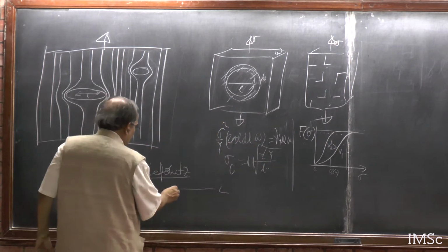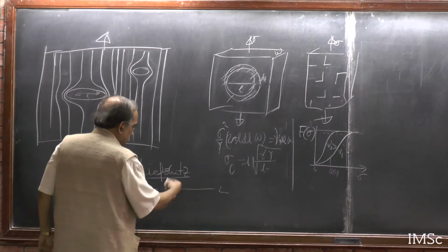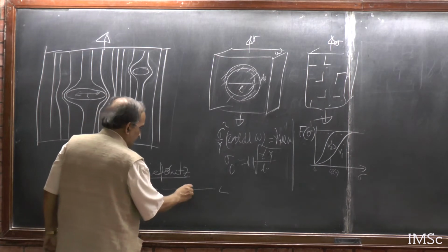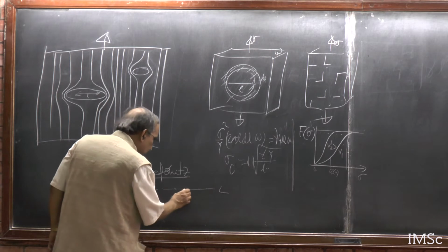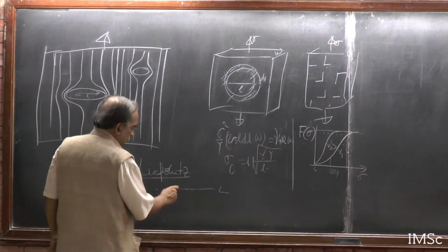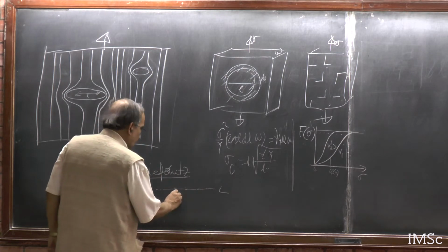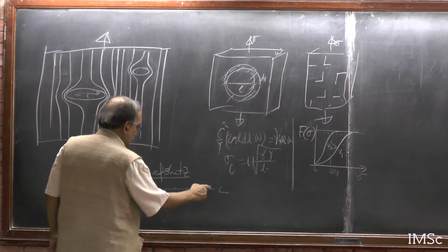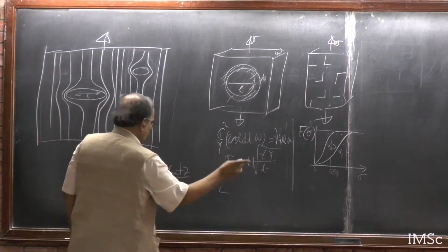And a simple argument was that if you have probability P of a defect, then to get two successive defects is P squared, with 1 minus P on both sides. To get three successive defects is P cubed, and then 1 minus P on both sides. So anywhere you want to do.